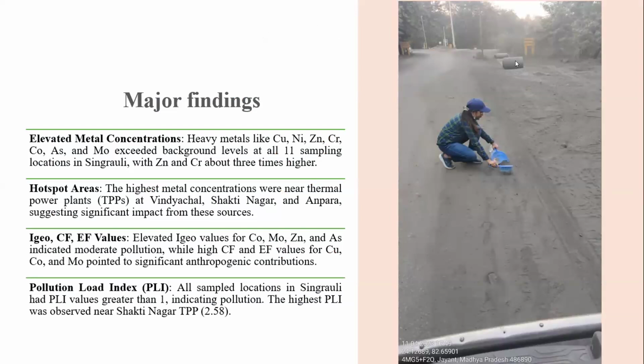From the Igeo, contamination factor, and enrichment factor values, the elevated Igeo values for cobalt, molybdenum, zinc, and arsenic indicated moderate pollution, while the high contamination factor and enrichment factor values for copper, cobalt, and molybdenum pointed to significant anthropogenic contribution. For the pollution load index, all sample locations in Singrauli had PLI values greater than 1, indicating pollution. The highest PLI value was observed near Shakti Nagar TPP, at 2.58.